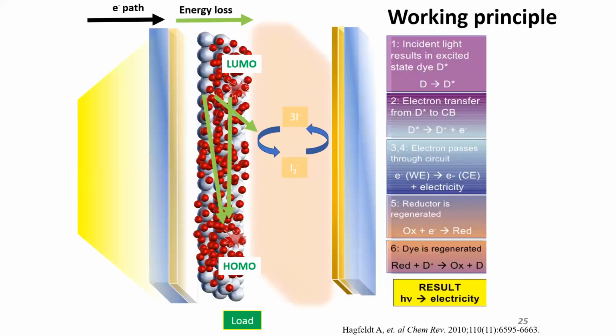But this is not that. There is some recombination also. We call that injection: sometimes the electron does not get injected from the dye to TiO2, and the hole and electron that were generated recombine back. And sometimes the electron that goes to the TiO2 recombines with the electrolyte. There is also the possibility that the electron from the conduction band of TiO2 recombines with the HOMO of the dye again.